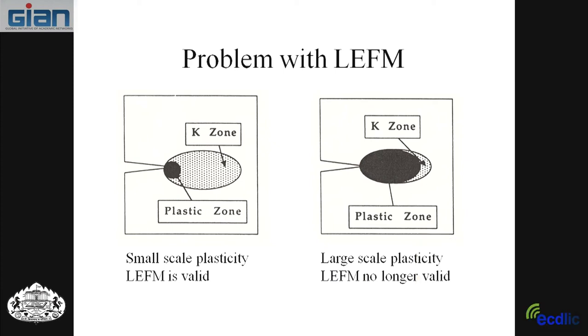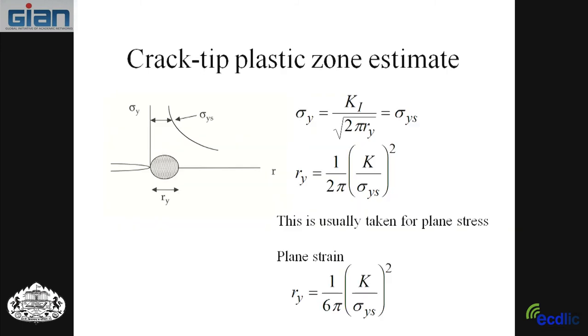So here, schematically, is what happens. You get a little plastic zone, and the K zone, which is the zone where all the action's taking place, the black box, dominates that plasticity, and the plastic zone doesn't cause any problem. However, if the plastic zone gets too big, then it wipes out the K zone, and with a small plastic zone, we have what we call linear elastic fracture mechanics. It's valid here. Big plastic zone, it's no longer valid. Now, how big is too big?